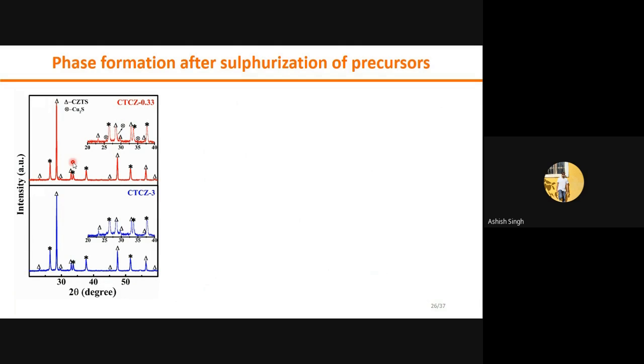So this is the XRD pattern of the sulfurized sample. In this XRD pattern, the star symbols are used for the substrate peak positions, the delta is for CZTS, and the circular cross is for copper sulfide. In the highlighted peak positions, we got the impurity phase of copper sulfide in this precursor, while in this precursor that phase is not present. In addition, unfortunately, the CZTS XRD peak positions are common with other impurity phases of zinc sulfide and Cu2SnS3 that cannot be distinguished by XRD alone. So for that we need to do Raman spectroscopy.